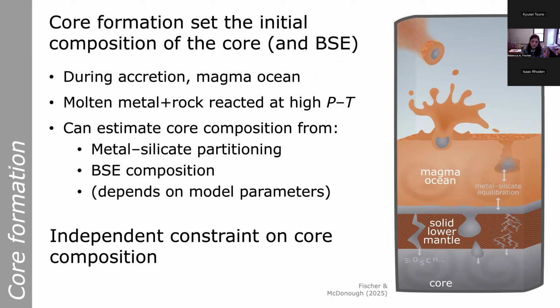So we can use this to sort of estimate what the composition of the core should be from its formation if we know something about these kinds of metal silicate reactions. And the key piece of information that we have here is the composition of the bulk silicate Earth, since this core formation process also shapes its composition. We know it has to come out matching what we see today. But as I will show you, the core composition you get from this depends a lot on model parameters. That is, it depends a lot on the details of how this process happened. But this is kind of a neat way to look at core composition because it gives you a constraint that is independent from the types of constraints I just described.